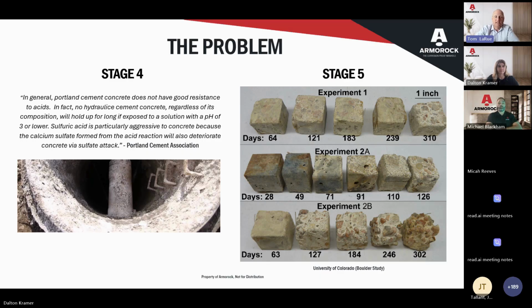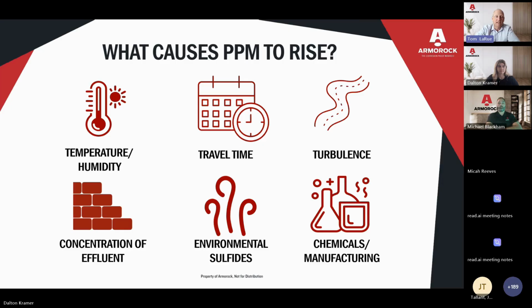So what causes ppm to rise? There are several factors. The Henry's law constants increase with heat and humidity. So higher temperatures, higher humidity, you're going to see higher ppm and higher corrosion. Travel time: the longer the effluent is flowing through a sewer line, the more time for that anaerobic activity to create H2S in the effluent for when it then reaches a turbulent point to be released into the atmosphere.